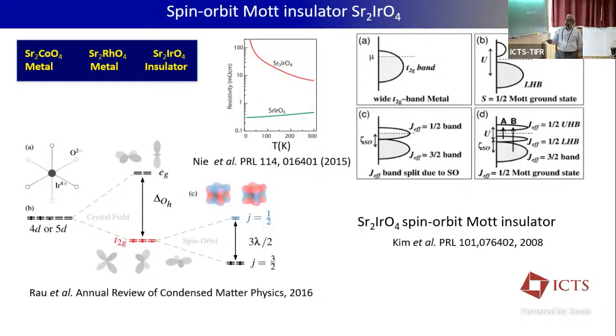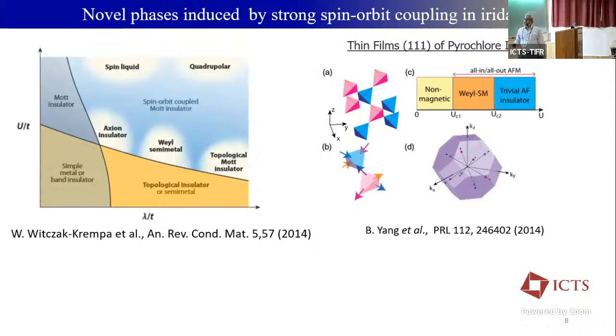This can be understood only by introducing the spin orbit interaction, because a J effective state comes into the picture when you introduce spin orbit interaction. When you switch on the Coulomb interaction, there is a gap forming in the J effective one-half band, with a lower Hubbard band and an upper Hubbard band, and that gives rise to an insulating character. So this is where the competition between the spin orbit interaction and Coulomb U opens up a gap, making Sr2IrO4 an insulator, and this is named the spin orbit Mott insulator. So there are many examples here.